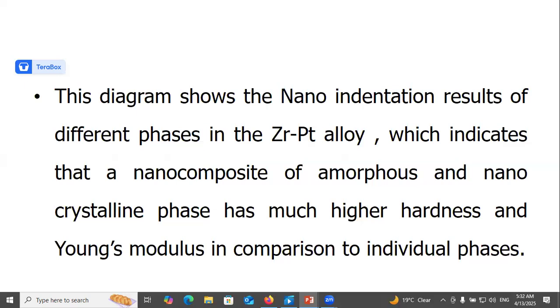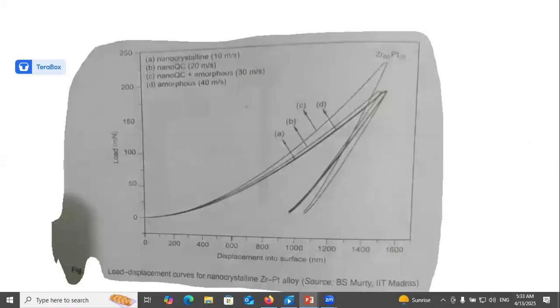The diagram shows nano indentation results of the different phases in the zirconium platinum alloy, which indicates that the nanocomposite of amorphous and nanocrystalline phase has much higher hardness and Young's modulus in comparison to the individual phases. This is the nanocrystalline, amorphous, and low displacement curves for the nanocrystalline zirconium platinum alloy.